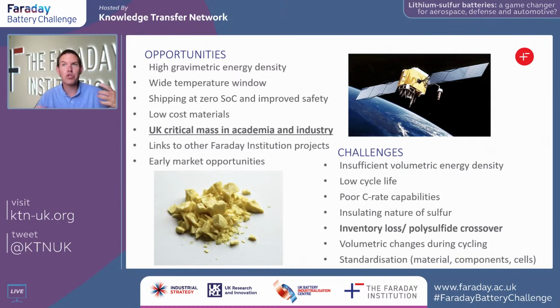And part of this strategy within the LiSTAR program is to think about new materials and materials engineering approaches to address some of these fundamental challenges with lithium-sulfur. Moreover, as we cycle lithium-sulfur batteries, we can lose inventory from our electrodes. There are large volume changes that happen during cycling. And so from a research perspective, we see that there is plenty to get our teeth stuck into, and that's obviously what we're trying to do in the context of the LiSTAR program.